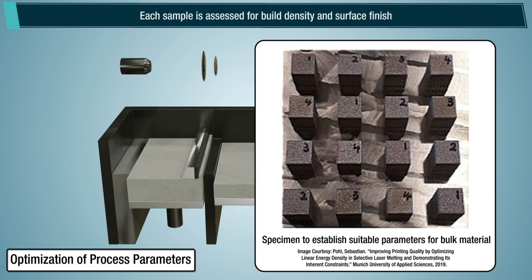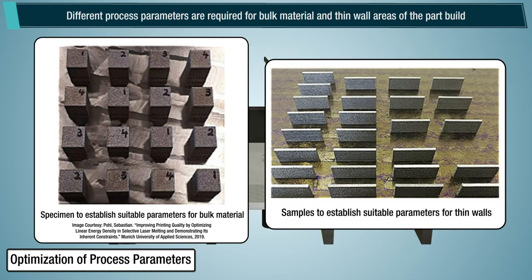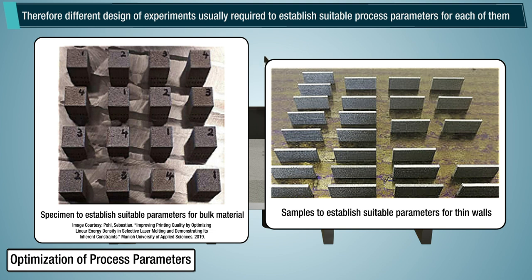Each sample is assessed for build density and surface finish. Different process parameters are required for bulk material and thin wall areas of the part build. Therefore different design of experiments usually require to establish suitable process parameters for each of them.